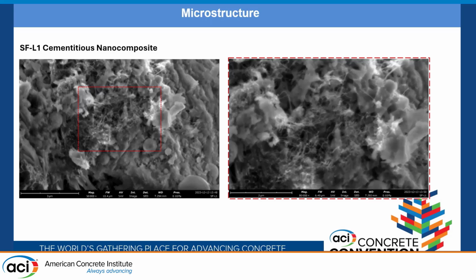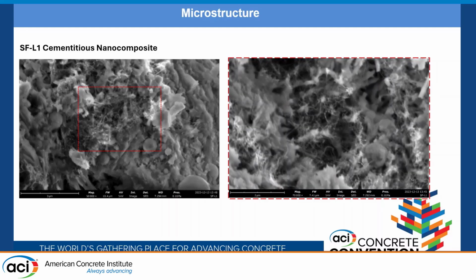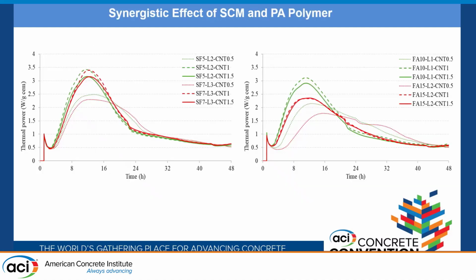So these are the samples that we took where we used silica fume as a carrier, and it does show under SEM that the nanotubes are dispersed quite a bit better in those cases. It does not, again, eliminate all the agglomerates, but it reduces them in our observation.